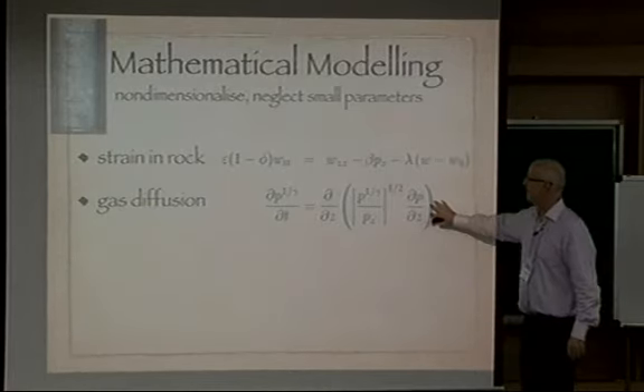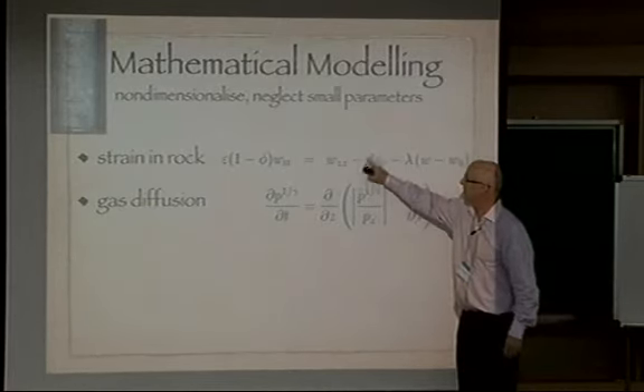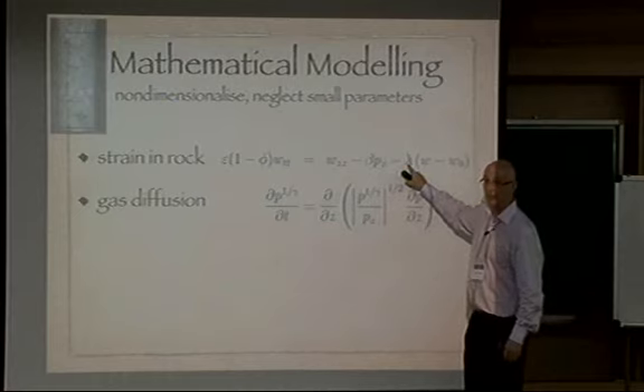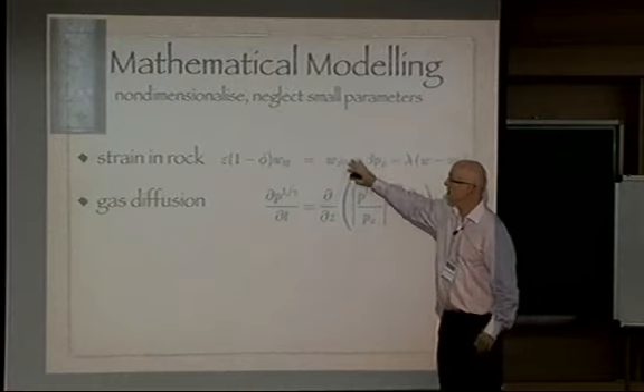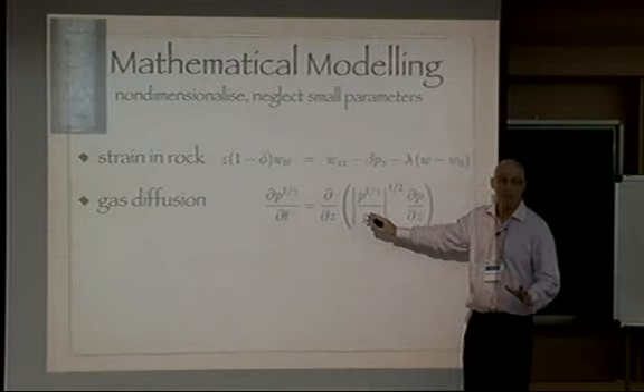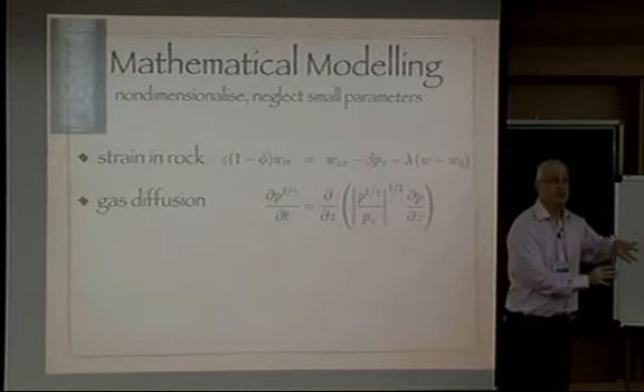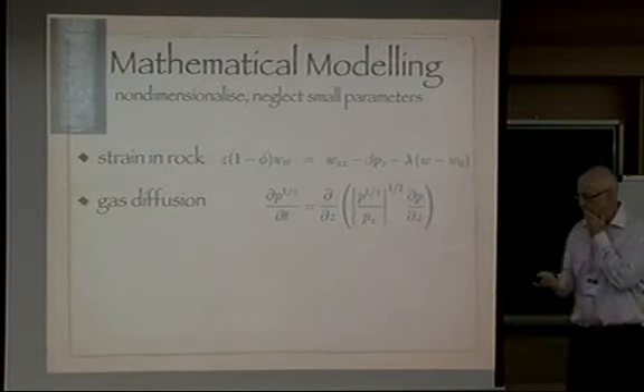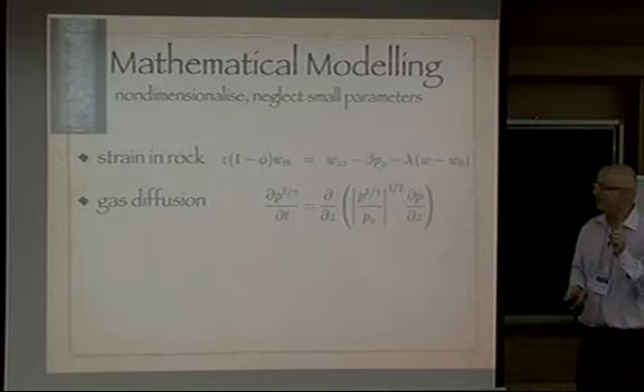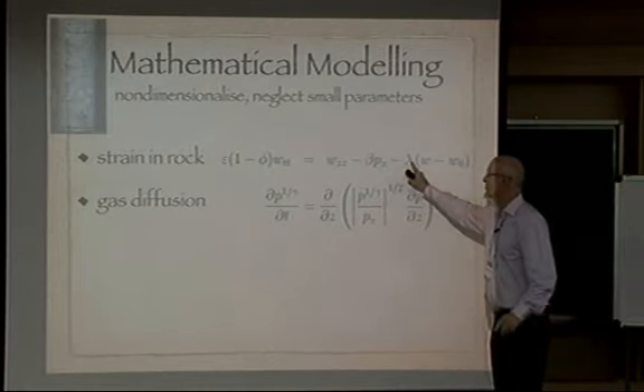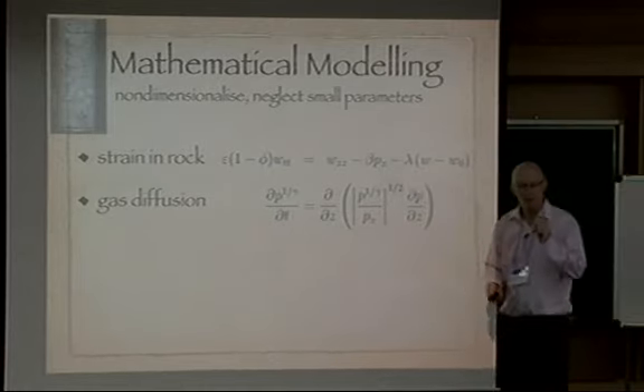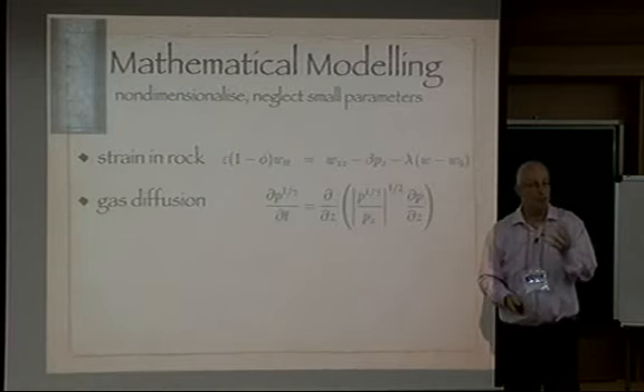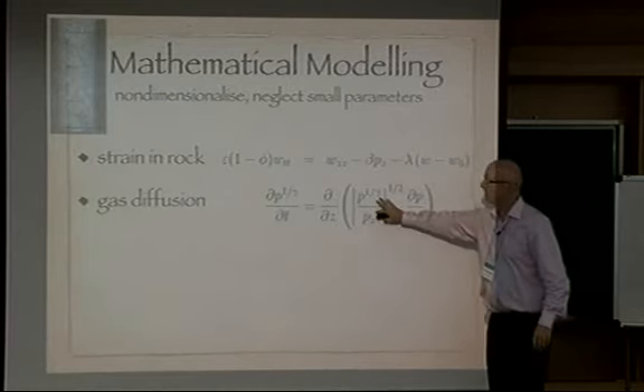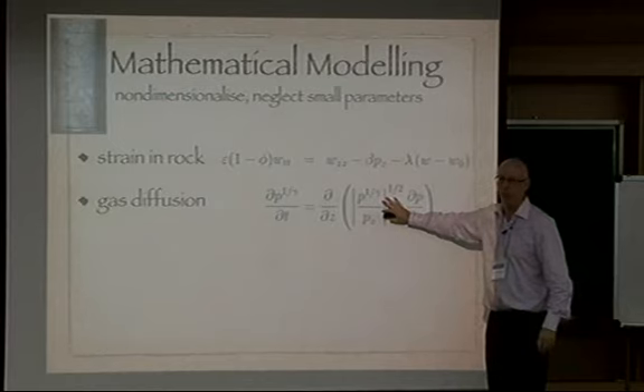So it's a very powerful technique. There are some parameters here. Beta is about 1. Lambda is the glue. It's of order 1. So almost no parameters are left in the problem. All the parameters are in the non-dimensionalization. Very powerful. There is, though, a parameter lambda, and we did explore the dependence on lambda. There is one more parameter, and that's the boundary condition, the rate of drop of pressure at the surface. It's very important.